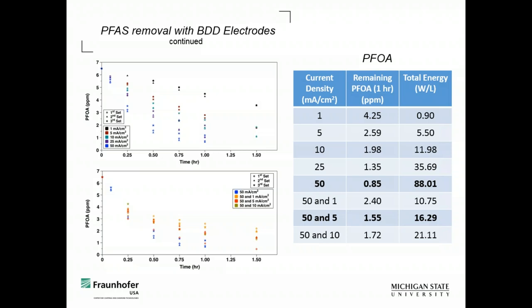However, if you look at 50, this says watts per liter because this is just a 1 hour test for these calculations, 88 watts per liter. If you extrapolate that up to 41 million gallons, we're talking about 13.74 gigawatts that would be needed per day to power a reactor to clean 41 million gallons of water. That's not going to happen. So we immediately wrote all that off, that it's not something where we're going to be able to fit.